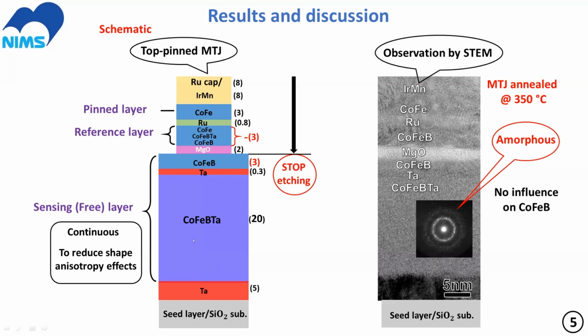We didn't actually etch the free layer, we kept it flat in order to reduce the shape anisotropy effect and make the magnetization in the free layer controlled only by induced magnetic anisotropy, which is produced during magnetic annealing. Okay, anyway, this is an observation of this layer structure by electron microscope. And as you can see here, this free layer is still amorphous even if we anneal this layer structure around 350 degrees Celsius.